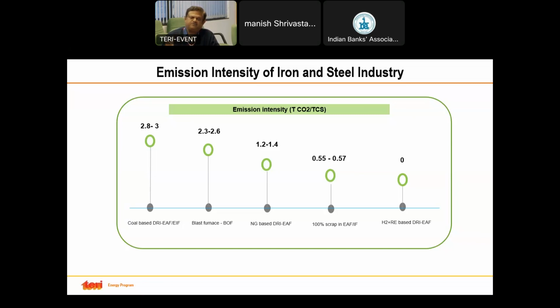As you move towards the right, the other technologies have lesser emission intensity. The blast furnace route has slightly less, 2.3 to 2.6, followed by the natural gas based DRI electric arc furnace route, which has 1.2 to 1.4. Here I would like to draw your attention: in the first bar, coal-based DRI has a very high emission intensity of 2.8 to 3, whereas natural gas-based DRI is nearly half the emission intensity compared to coal.